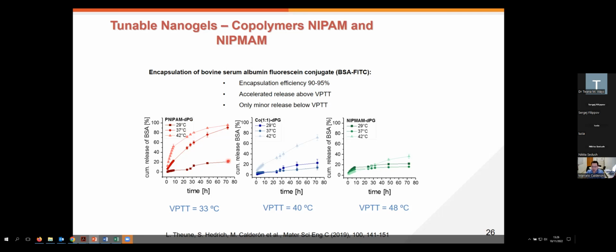When we work with the copolymer 50-50, we have a transition around 40 degrees. So now when we incubate this at 29 and 37, the release is not that prominent as compared to whenever we cross the transition temperature at 42 degrees. And when our nanogel now has a transition temperature that is much higher, so when we incubate at these two temperatures, then the proteins have almost no release, only a very marginal release over this very long window of time. So they're somehow encapsulating the proteins and releasing them with the behavior we were expecting.